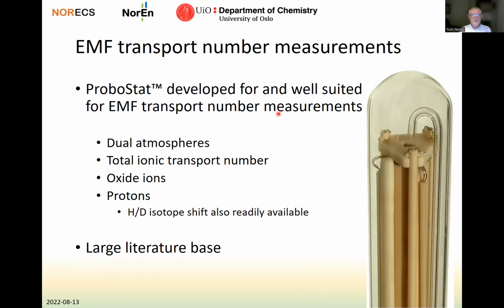The ProboStat was developed for and is very well suited for EMF transport number measurements, where you establish dual atmospheres and measure the EMF, the electromotive force, and from that obtain the ionic transport number. Then you set the cell up like this. You have your sample in here, you supply one gas to the top and one gas inside to the bottom electrode, and you measure the voltage over there. This is typically used to study oxide ion transport numbers, but you can also study proton transport numbers by using different water vapor or hydrogen partial pressures. And the ProboStat can, of course, also be used to do hydrogen deuterium isotope shift measurements to get further information about proton transport. There are many papers on how the ProboStat is used for these kinds of measurements.